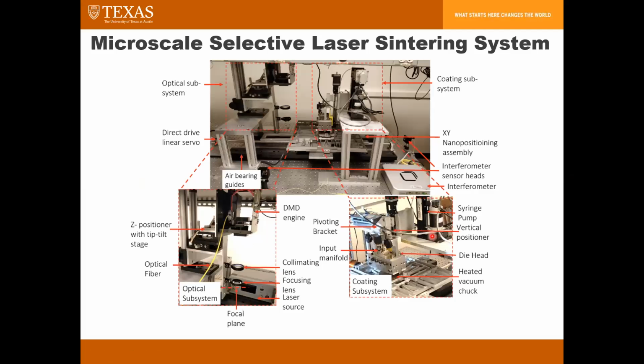So here's an overview of the system. On the right over here, we have a slot die coating system, which lays down a thin layer of nanoparticle ink. Right now we're using copper and silver. That's laid down onto a substrate, which rests on top of this nano positioning stage here in the middle. This gives us XY control during sintering.